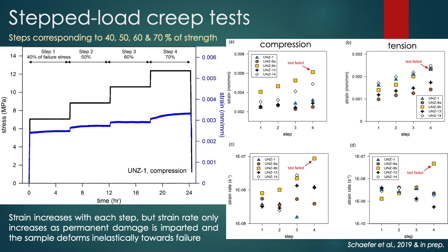The plots on the right summarize this data for the whole series of tests in terms of both strain, strain rate within each load-hold portion, and for all the tests at different samples in compression and tension. Although the strain increases from one step to the next in all cases, you can see that the strain rate only increases for a few tests at the 70% load-hold portion, meaning that at values below that, no permanent damage should be imparted on the samples. This is important for the next suite of tests.